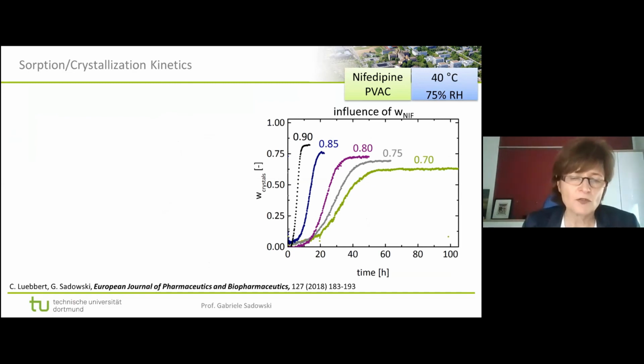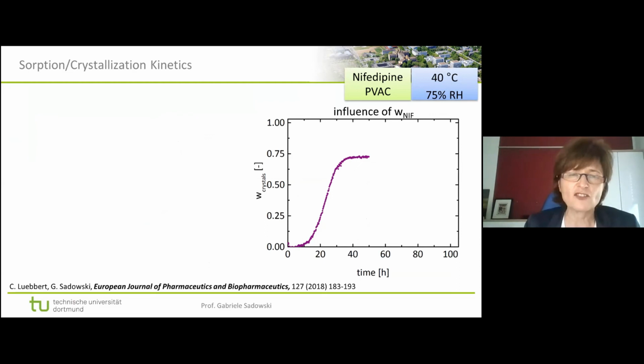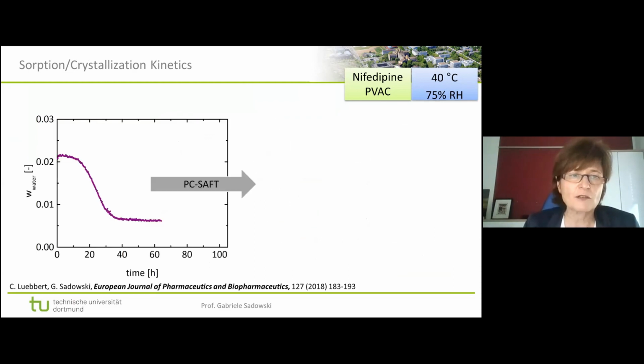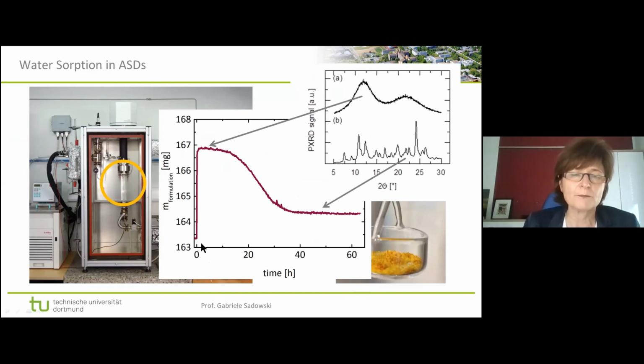We did water sorption measurements. Actually, this is the result of a water sorption measurement you see here. This is a nifedipine system. So what you see is that this is the water sorption of the amorphous nifedipine, and this is the water sorption of the equilibrium crystallized nifedipine. This is nifedipine in a polymer, of course.